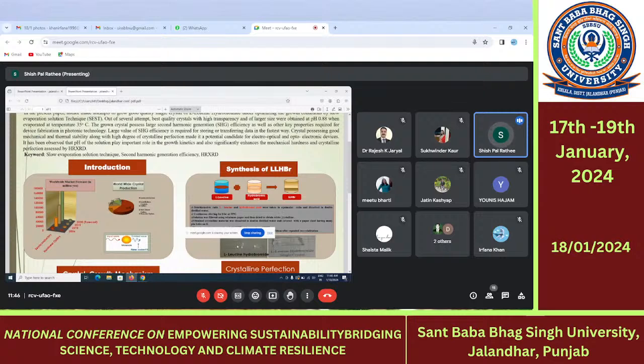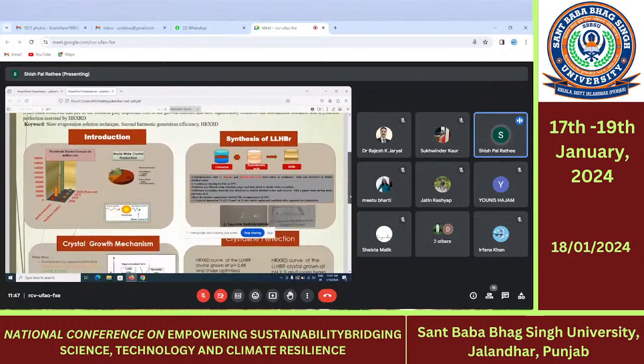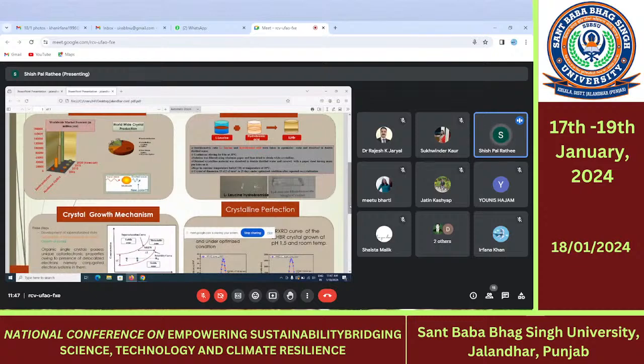It is only like a transparent film type, and as we change the value of pH to different values, and we have taken photographs of the crystal, as the pH value decreases, the quality of the crystal increases, meaning the thickness of the crystal increases as well as the mechanical strength.